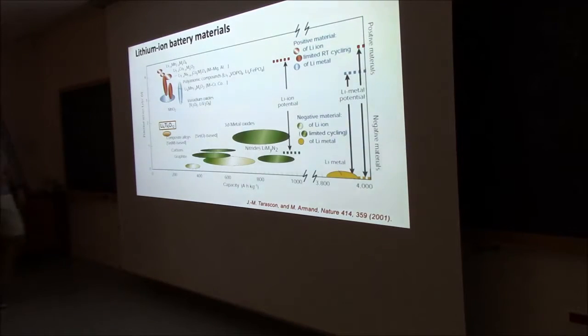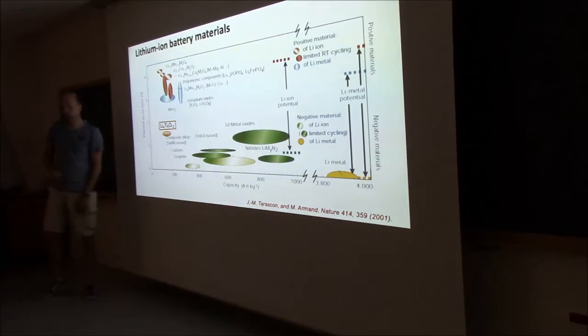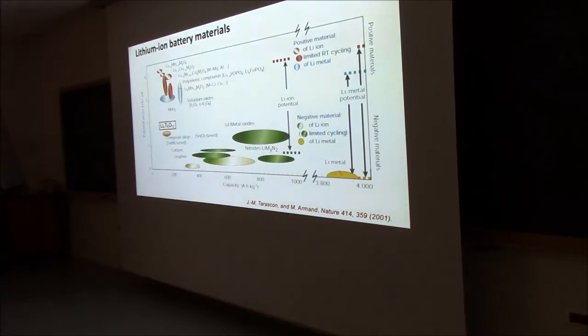So what I wanted to show is the anode material, which is interesting. So it's the lithium titanate. But you can see it positioned here. It's 1.5 volt. So compared to these two, the voltage is way too high. So would not be a very good choice. However, this material allows lithium to move in and out extremely fast. So for some applications, that's very interesting to use.